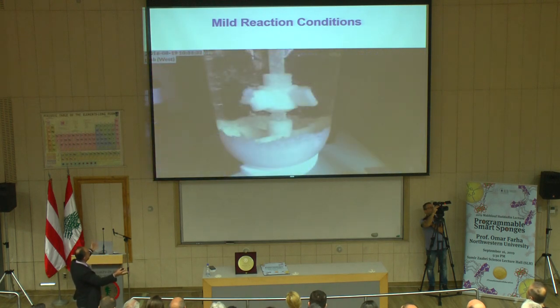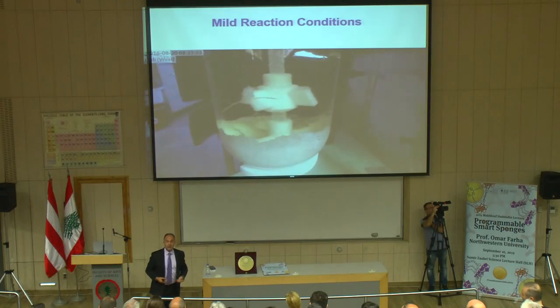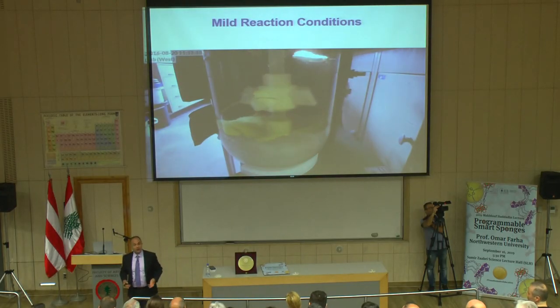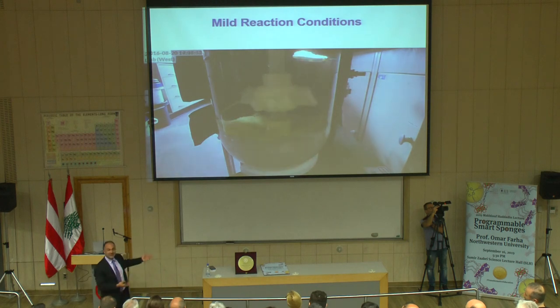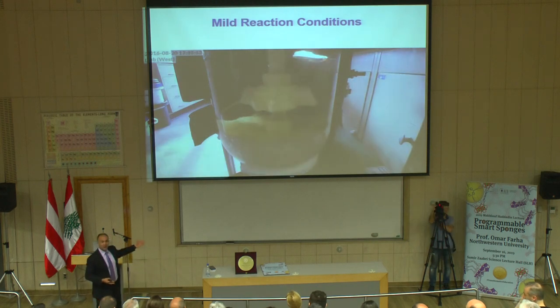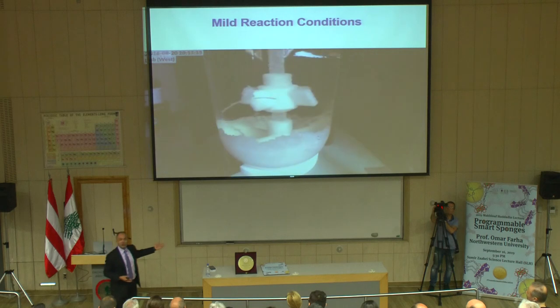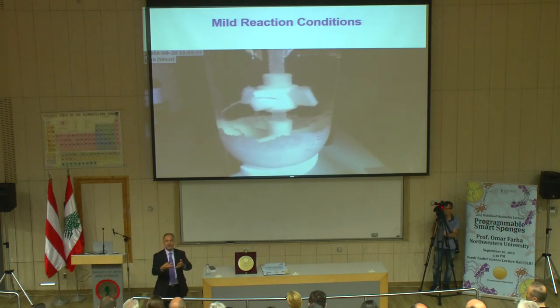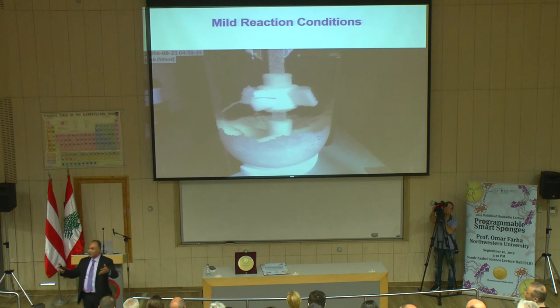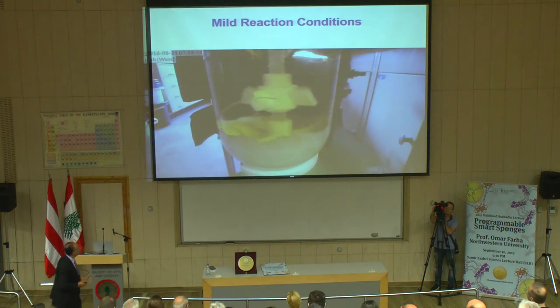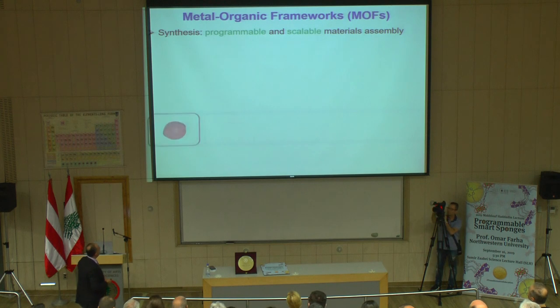Very quickly, you saw cloudy, it dissolves, then starts to crystallize, and each one of those is a beautiful single crystal. What I'm trying to get across here is that the reaction conditions are so gentle that you could do it in these glass containers and actually with your iPhone monitor the reaction from your home, watching the crystallization of these materials literally taking place, from the micro into the micron and the millimeter level.